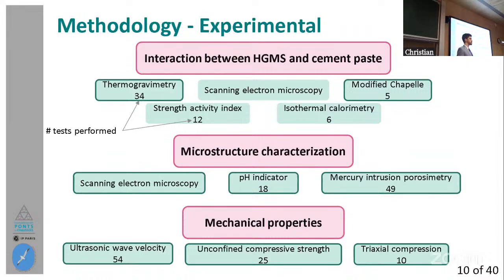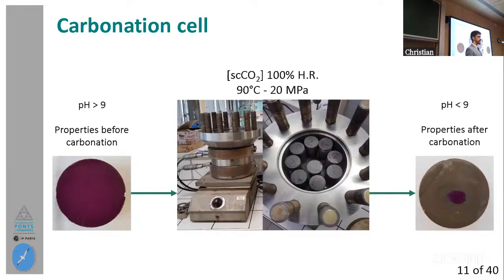Also in the numbers there, you will see the number of tests performed in each of them. I have talked about carbonation, and for doing that, what I have used is this carbonation cell that is present here at the École Nationale des Ponts et Chaussées, in which I was able, as you can see here, to put my cylindrical cement specimens and then subject them to a high pressure of 20 megapascals and a high temperature of 90 degrees centigrade in a CO2 saturated atmosphere with the presence of water.